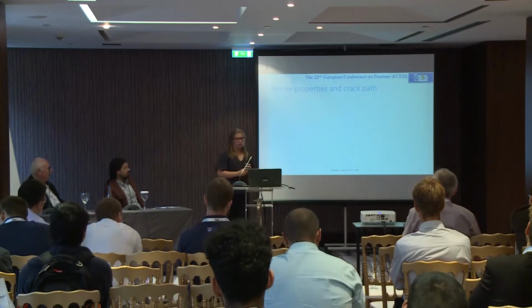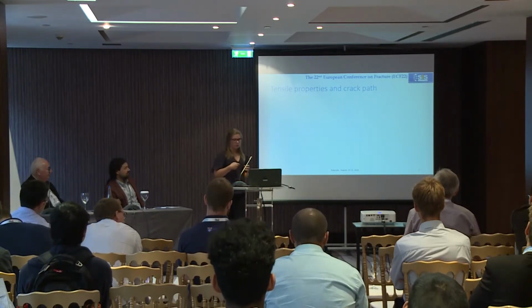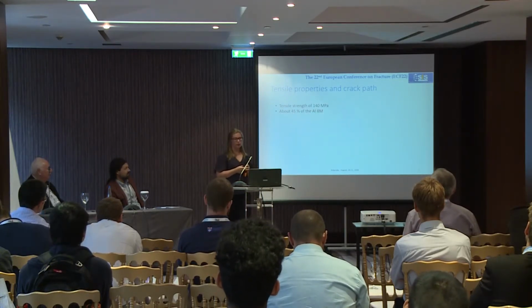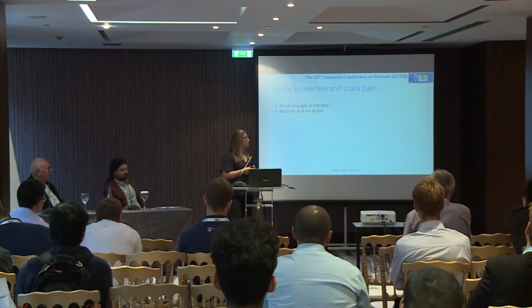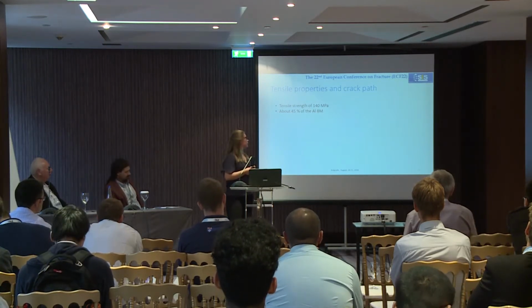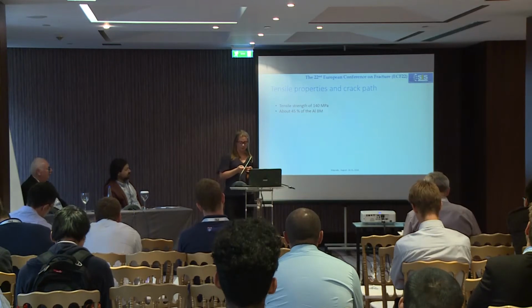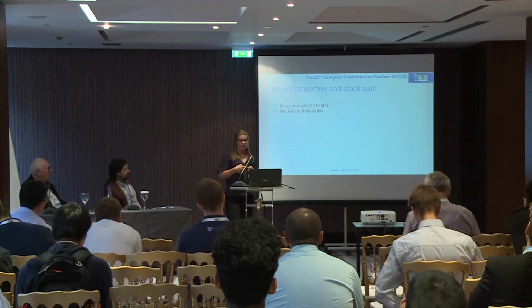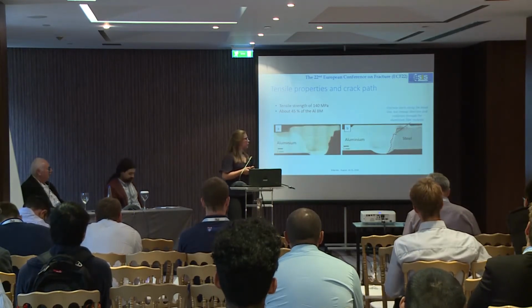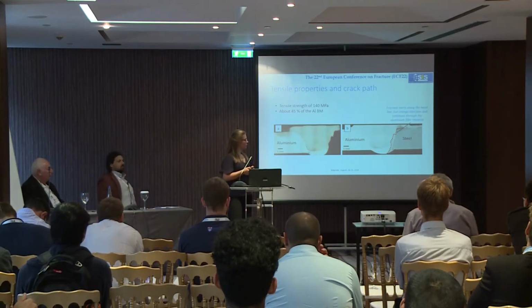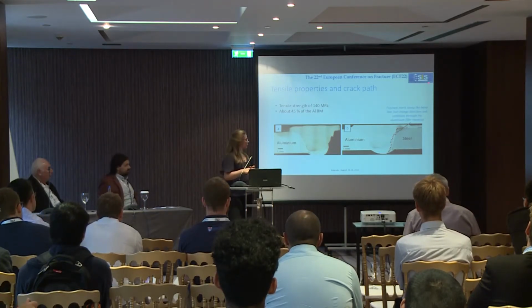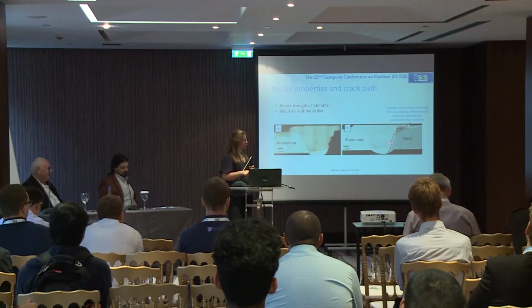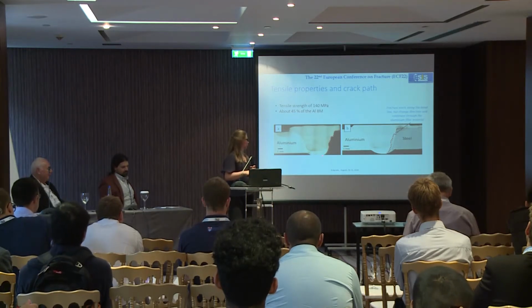So the tensile properties of this joint were found to be 240 megapascals, which is about 45% of the aluminum base material. But what was really interesting is the fracture path of these joints. As you can see, the fracture starts along the bond line, but it changes direction and continues through the aluminum filler material. Yeah, you can see it.